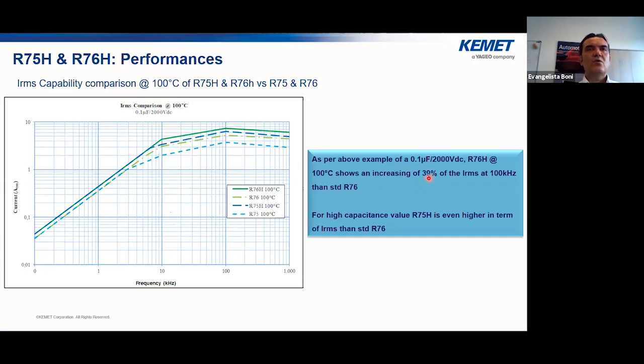R76H, for instance, can work with up to 30% more current versus the standard R76. And for high capacitance values, the R75H has higher ripple current than the standard R76. It's possible to see this in the graph, where the ripple current is plotted at different frequency levels.